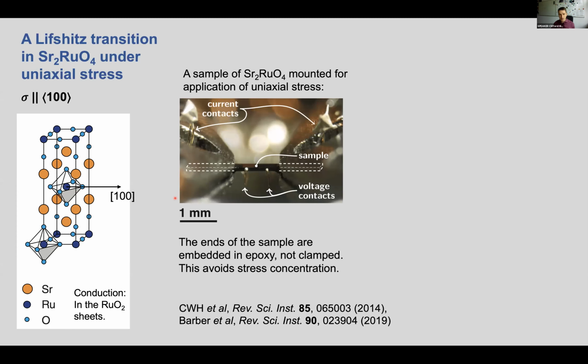This is what the essential experimental setup looks like. The sample is a relatively long and thin bar, and its ends are embedded in epoxy. It's very important that the ends are not clamped. They're embedded in epoxy, and that provides a conformal layer that avoids points of stress concentration. And that lets us reach very high stresses with very high stress homogeneity.